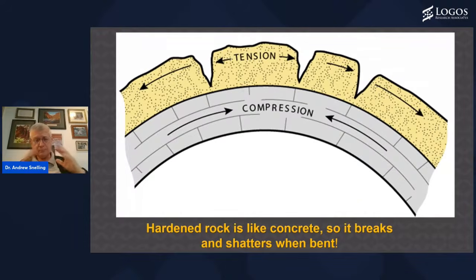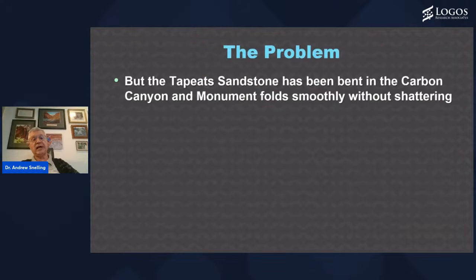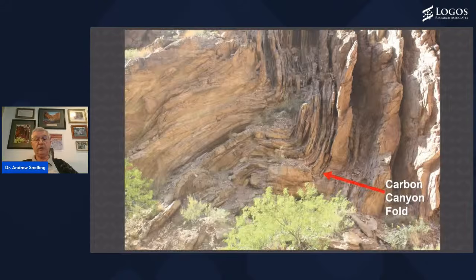They're deposited with the grains, then the water that's carrying them is trapped in between the sand grains. That carries chemicals, and then when the rock dries out, those chemicals precipitate and bind the rock together to make it hard. And so hardened rock will shatter. But here's the problem: the Tapeats sandstone has been bent in the Carbon Canyon and Monument Folds smoothly without shattering. We can see that again here. You can see in the hinge zone, the bend zone, that there's a nice smooth layering there in the Carbon Canyon Fold.